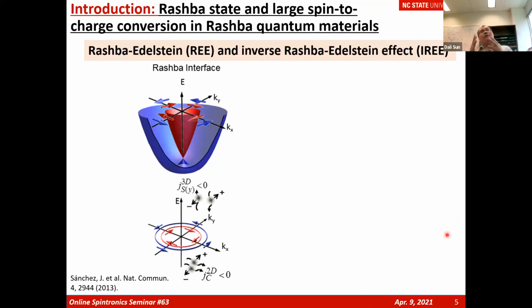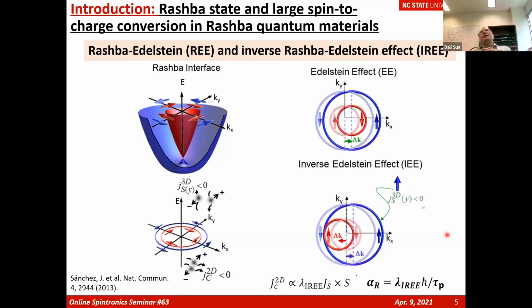Actually, people realize that if we're forming a typical Rashba state, whether caused by an interfacial or bulk Rashba effect, and you induce a three-dimensional spin current into the Rashba state, you will generate a transverse electric field through the inverse Rashba-Edelstein effect. So it turns out the spin-to-charge conversion efficiency in a Rashba state is very efficient compared to the spin Hall effect in heavy metals like platinum, tungsten, or tantalum. So Rashba states act as very efficient spin-to-charge converters.